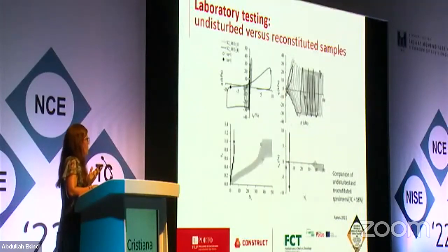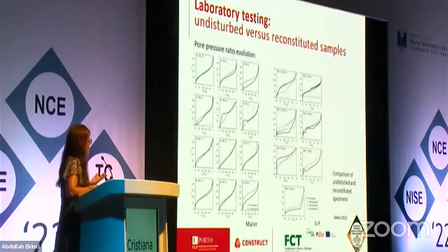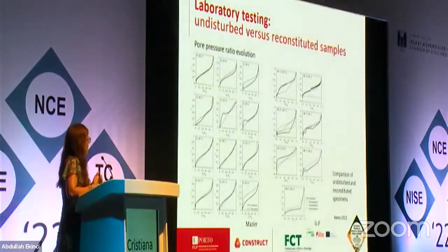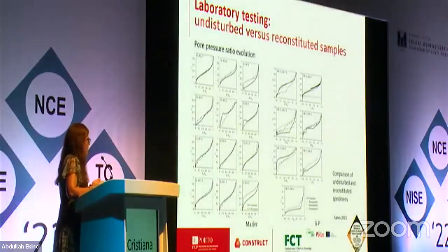18%. And this was analyzed for a large number of specimens, and we also did studies on the pore pressure ratio evolution. This is just a very quick view to show that in some cases we have a very similar response, in terms of the number of cycles and the evolution of the pore pressure, and in other cases we have a very distinct result from the undisturbed to the reconstituted specimen. And this brings us back to the things that we cannot control and reconstitute in the laboratory, which is the natural fabric and structure of the specimen, especially in the case of interlayering or interbedding that we observed here, and in some cases more than others. Typically, when we have a higher fines content, we have more layering, and with lower fines content, we have a more homogeneous specimen.